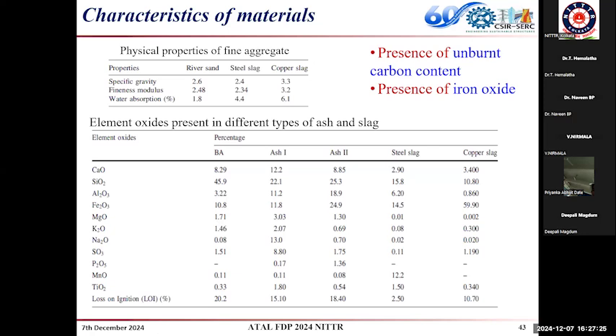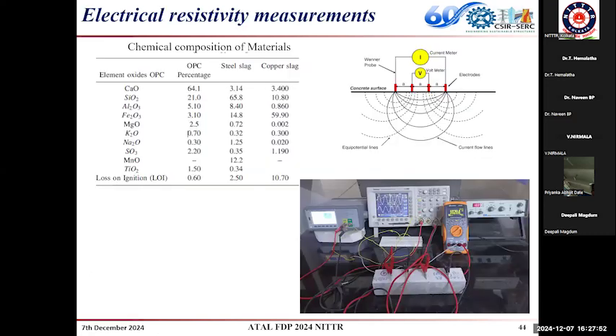So based on this, for the different materials we have chosen, we have carried out an element oxide test for finding out the element oxides. Here Fe2O3 content is high in many of the materials. If you see the copper slag, it has around 60%. So it was actually providing good electrical conductivity.